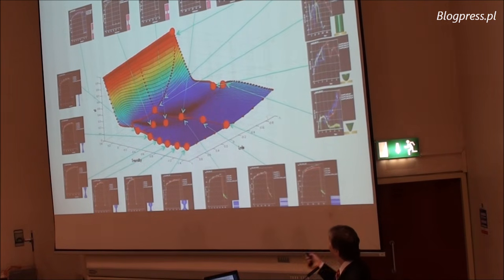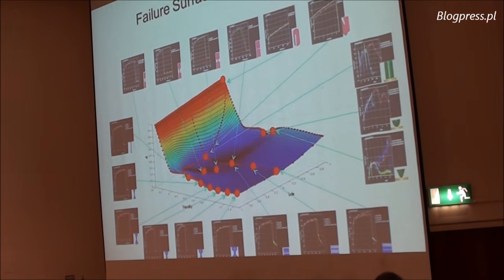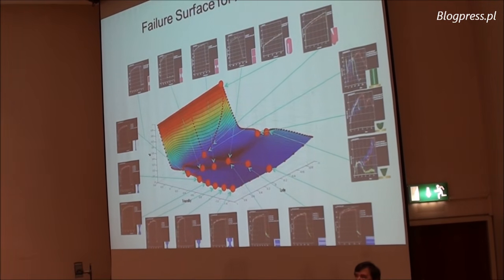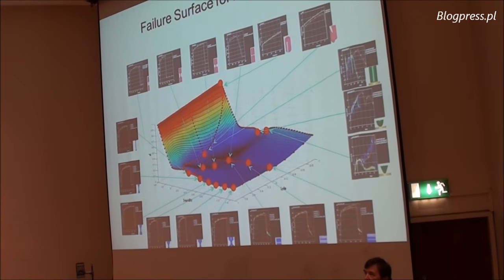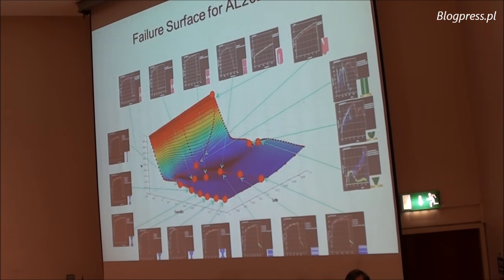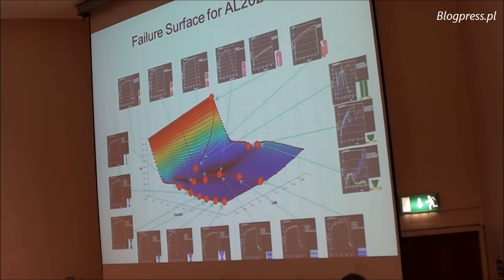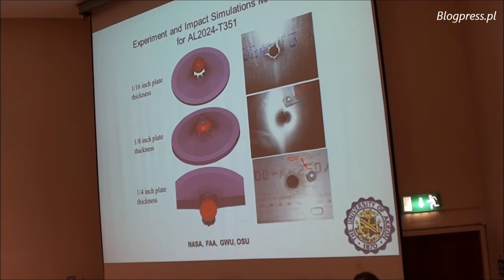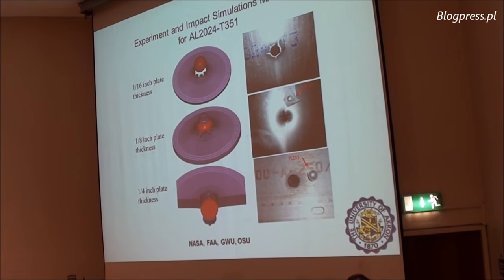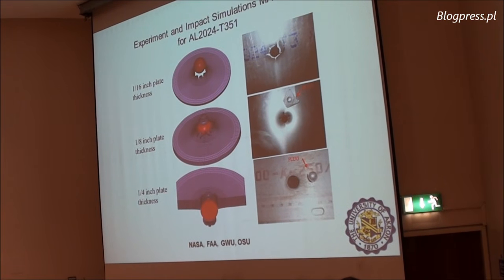Now, all of these tests that are shown at the outside of this slide are needed to produce the so-called failure envelope. So this is the failure surface for aluminum that shows how dramatically different failure can be depending on the combination of the state of stress that you apply to this material. Once this material is characterized, it is put into LS-Dyna as a so-called tabulated material model 224, which means that the experiments are completely embedded in the numerical model.